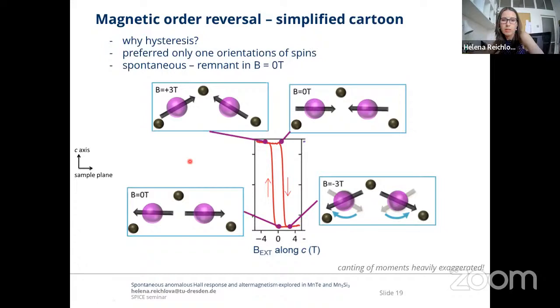When we apply a high magnetic field of 3 Tesla, the spins are canting in one direction. Then we reduce the magnetic field to zero, and the spins are in this orientation. We reverse the polarity, we apply a high magnetic field in the opposite direction. The spins are originally pointing in this direction until the moment that they can flip to the energetically more preferred orientation, which is marked by this arrow, and then sweeping the magnetic field back to zero, we are in our second spontaneous state. I just want to highlight that the canting of the moments is heavily exaggerated and that the effect is present also in zero magnetic field.